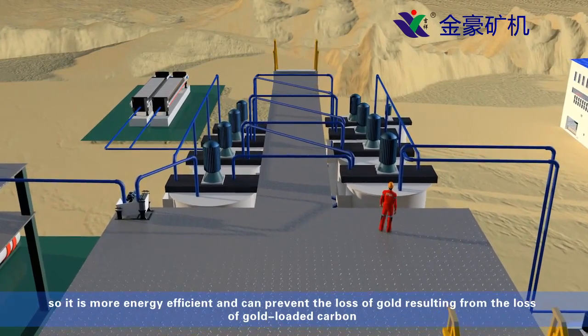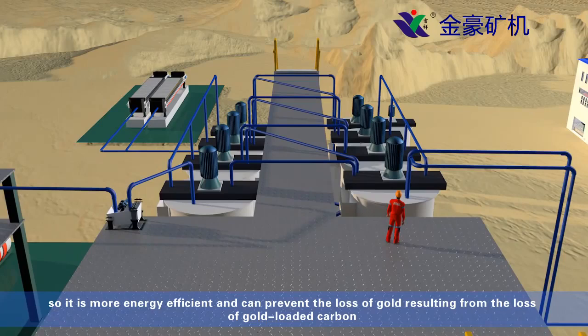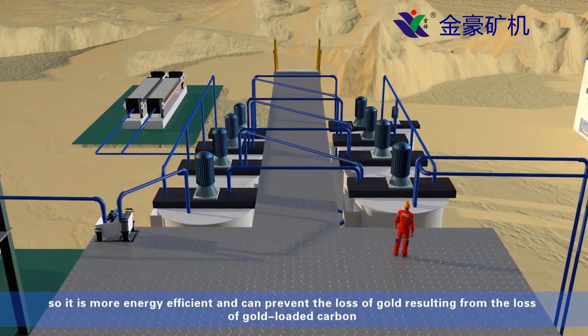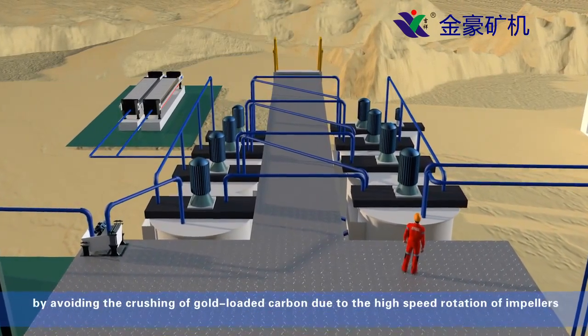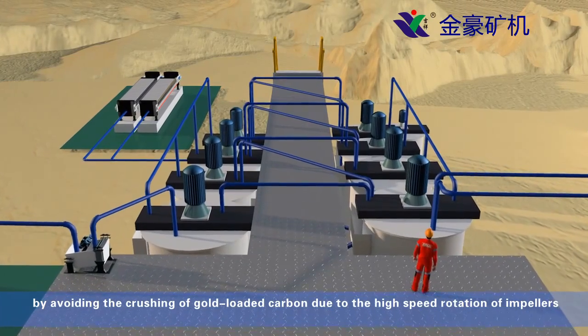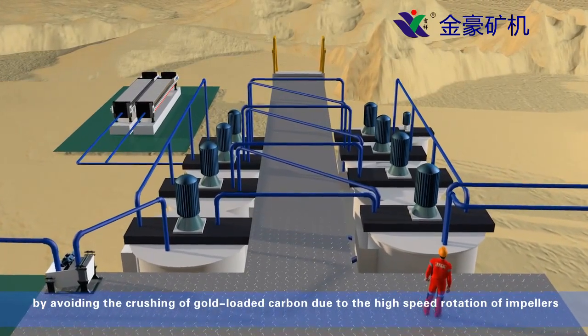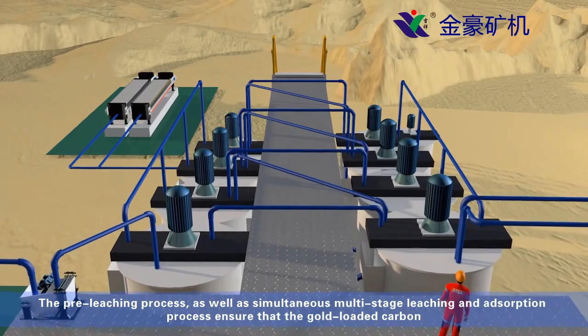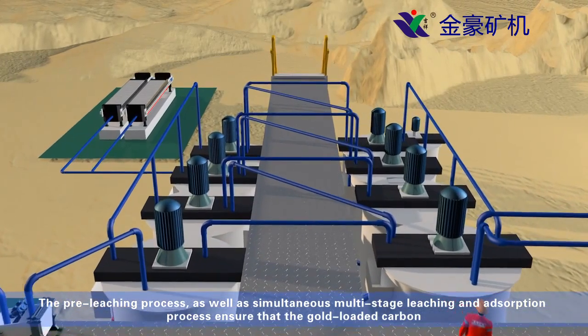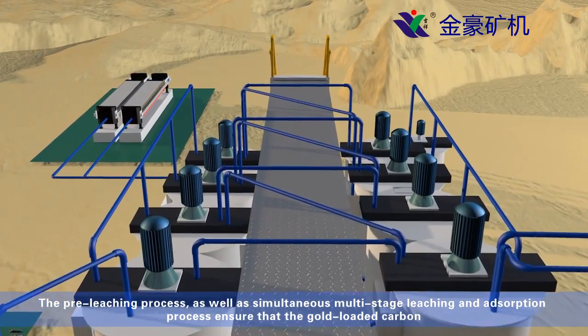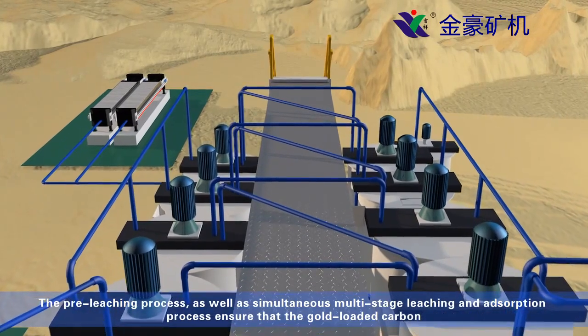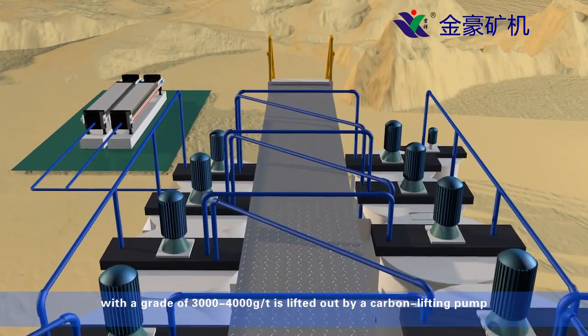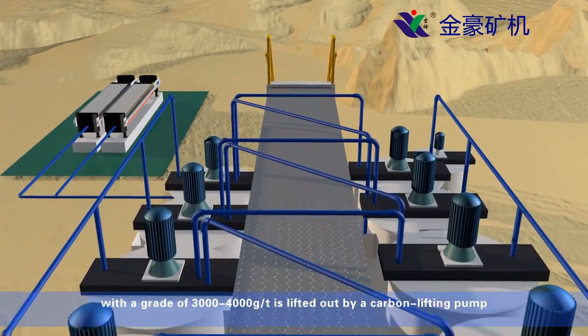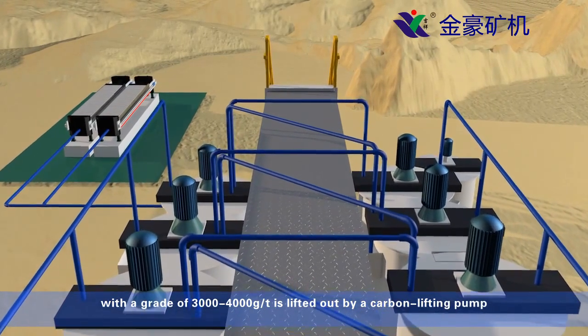So it is more energy efficient and can prevent the loss of gold resulting from the loss of gold-loaded carbon by avoiding the crushing of gold-loaded carbon due to the high-speed rotation of impellers. The pre-leaching process, as well as simultaneous multi-stage leaching and adsorption process, ensure that the gold-loaded carbon with a grade of 3,000 to 4,000 grams per ton is lifted out by a carbon lifting pump.